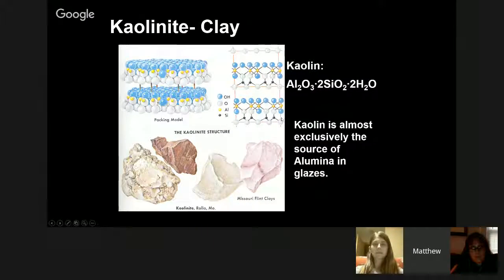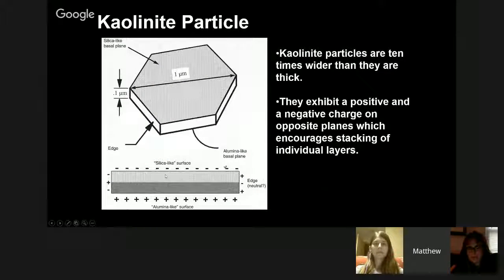Okay, and then they're bonded by having extra hydrogens and oxygens in there, which come in the form of chemically bound water. So this is really important because each one of these materials has a different surface charge. Okay, the silica surface is negative and the alumina surface is positive. And that's important because that makes our clay into these little magnets, which is the whole reason why clay works as we know it, that it sticks together and you can shape it at room temperature because all those little particles are basically little magnets that stick together.